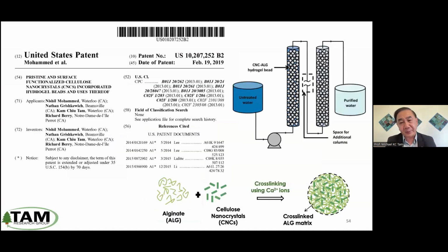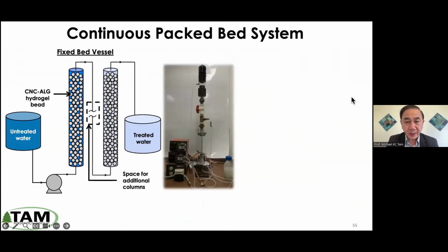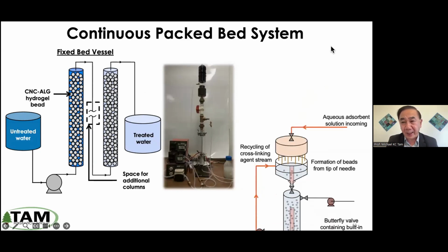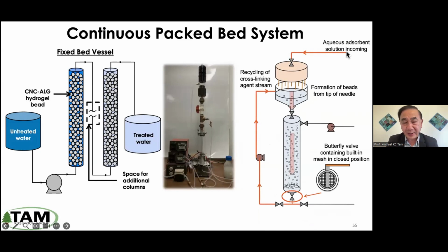So now we want to scale. We want to develop a process that we can then build into a system. So here is the continuous process. We have untreated water. We want to put these beads into a column and just pump the water through, and then we have cleaner water on the other side. Okay. So my PhD student, Nate, built this system. We want to have a demonstration of a pilot concept where we make the bead in situ, right? So how do you do that? We build a system where we have this alginate and our CNC extruded into a dilute solution of calcium chloride, right? This has 35 nozzles that we extrude, and then the beads are formed, and then they are transported to the column. When the column is being filled, then we stop the production and we do the processing of the water, and that can be done continuously by control of the valves.